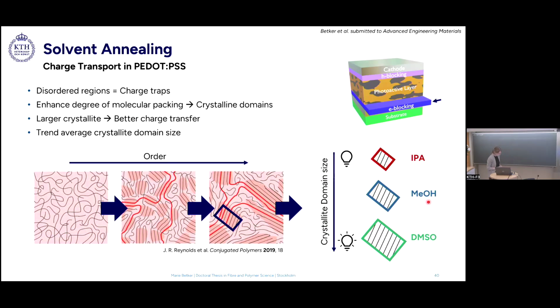However, the conductivity of such an electrode does not only depend on the percolation, but also on order. So in polymer films, the degree of order is really important for the conductivity. On the left side, you have a completely amorphous polymer film, so no order at all, no conductivity. But when you then increase the order, which we did by spraying these organic solvents on top, you actually enhance the order by enhancing the degree of molecular stacking.